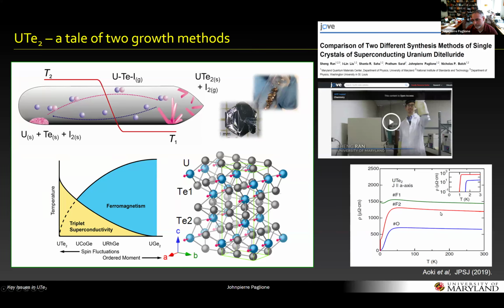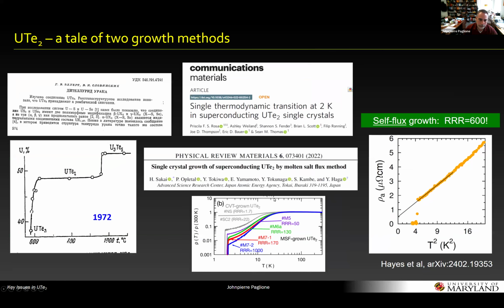And from Aoki's first paper that reproduced our work, it's also apparent that you can slightly change the growth parameters and get superconducting crystals and not superconducting. So this is nothing new. And as I said, if you look at the old literature, you can already see, for instance, in the 70s, this Russian paper, we're just tuning the growth temperature. Actually, there's a span of temperature range where they claim to grow UTe2 the right phase, but then nearby there's other phases that form. And so you have to be very careful about this. I think I made a slide. Oh yeah, I'll get to a slide about the other phases of uranium tellurium that we constantly worry about, actually.